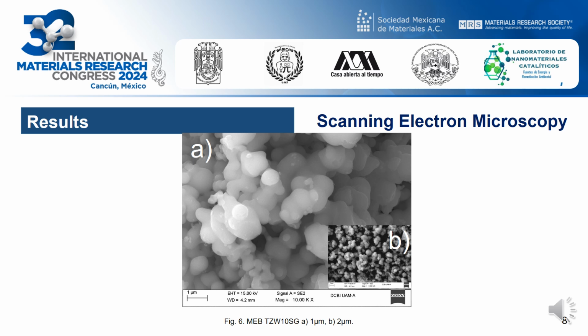And finally, it was found that through sonochemistry, it's possible to reduce the synthesis time from 80 hours by sol-gel to 18 hours by sonochemistry. In addition, the characterization results show that the materials obtained via sonochemistry preserve the best characteristics, making them ideal for carrying out the production of biofuels.